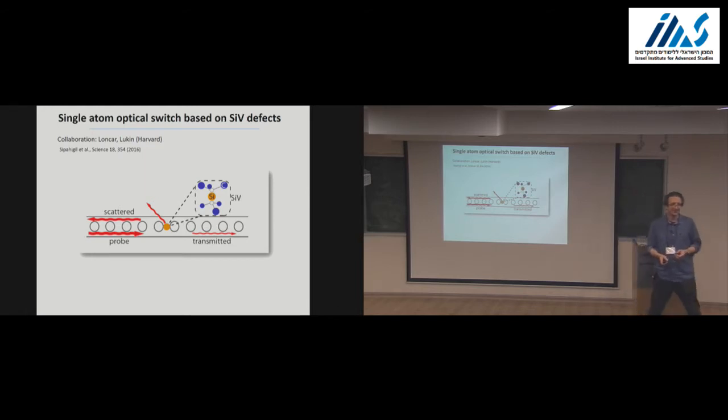If you compare the coherence times in silicon and germanium, how do they behave? Experiments in millikelvin have not yet been done for germanium. So I think it's a difficult question to answer at the moment, but from the energy level structure and all the photophysics, both defects are very similar. So for the germanium vacancy center, we would also expect that by cooling it to a few hundred millikelvin we would freeze the orbital dynamics and reach millisecond or longer coherence time.